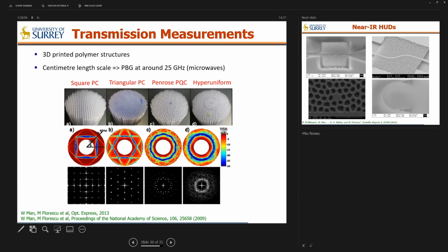In the case of the hyperuniform lattices, this asymmetry has been removed, and I have nearly perfect radial symmetry of the transmission. So it means that for a frequency in this range, the band gap occurs exactly at the same values for the frequency, regardless of the angle we are looking at. And these photonic properties follow quite closely the scattering properties of the system. This is a two-dimensional structure factor, just a Fourier transform of the dispersion present in the structures.